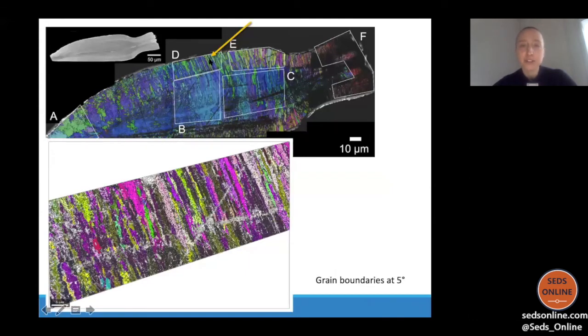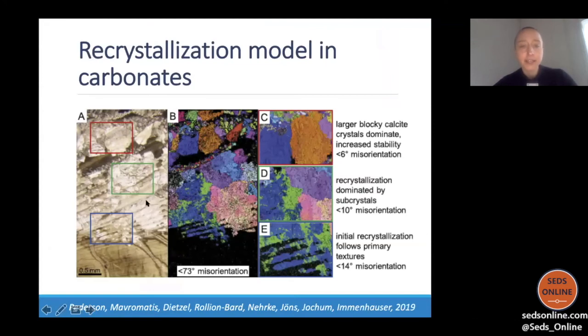this is probably the original texture. And as you go towards the front, you see these increased grains and decreasing range of misorientations. But for phosphate, we don't really have good diagenetic models. And also one big difference is in carbonates, we have the metastable aragonite, which obviously recrystallizes, but apatite does not have this duality. There's only one mineral, which should be stable.